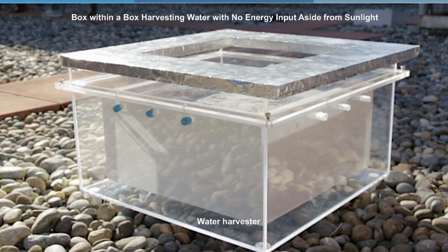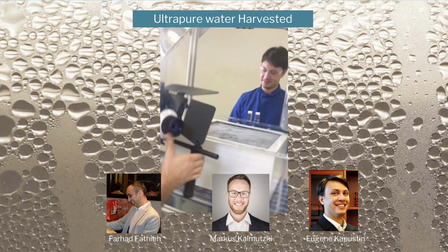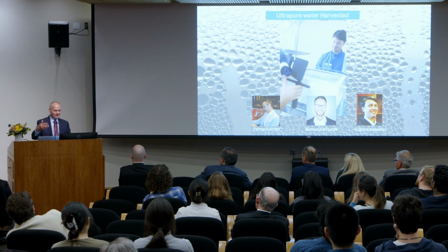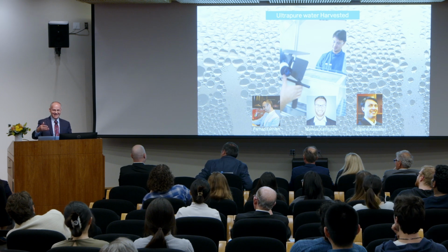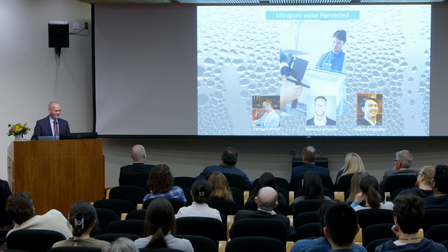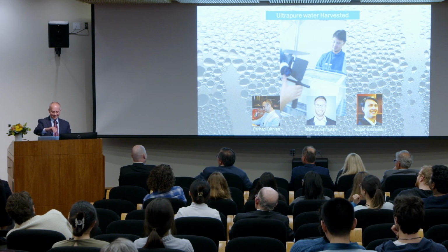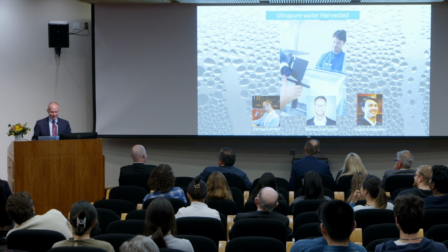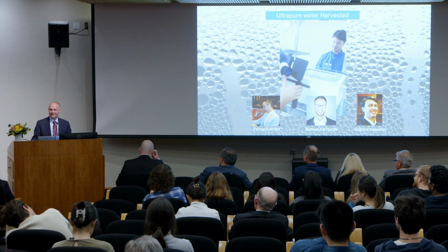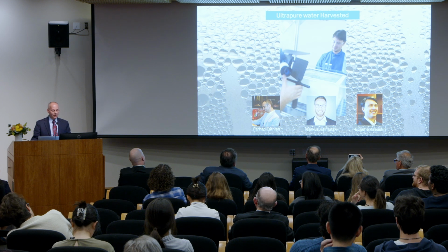That's what the box looked like. And my 3 heroes at the time, coming from various parts of the world, rented a black SUV in the Bay Area and in Berkeley and drove with their device, with all the wires coming into the device and out, as you know, to measure the humidity, temperature, and all of that. And of course, I sent a letter with them that said that this white powder, this 1 kilogram of white powder, is actually a legitimate experiment and there is nothing to be suspicious about, in case you are stopped by the sheriff along the way. Well, you've had very interesting people going to this experiment. Well, they did the experiment